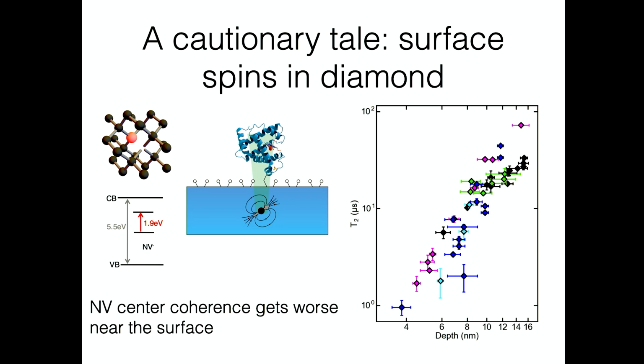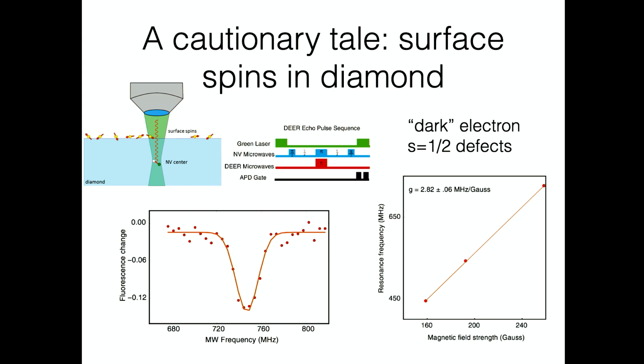So if you had asked anybody in 2011, maybe, or something like that, what is the cause of this noise at the surface that screws up my NV centers, they all would have given you the exact same answer, which is that, oh, I can do a measurement of this noise. It's very, very easy. If I do a Hahn echo coherence measurement on my NV centers and then use another microwave tone to probe what else is in the bath, then I can see a little signature of these spin 1/2, g=2 electronic spin defects at the surface that are probably things like dangling bonds or something like that.